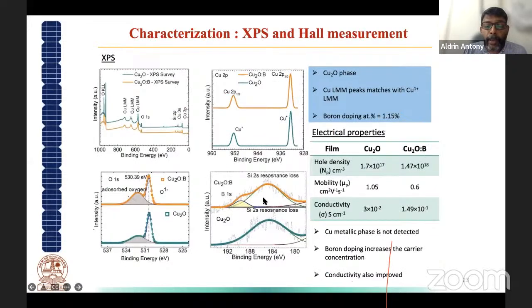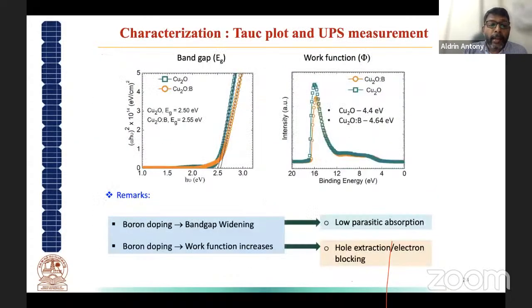And if you compare the different, I'm just skipping this slide. This is actually how you identify the band gap of the material and the work function of the material from the UPS analysis we have found out. And it is something around 4.4 electron volt for copper oxide, and with the boron doping, it is 4.64.